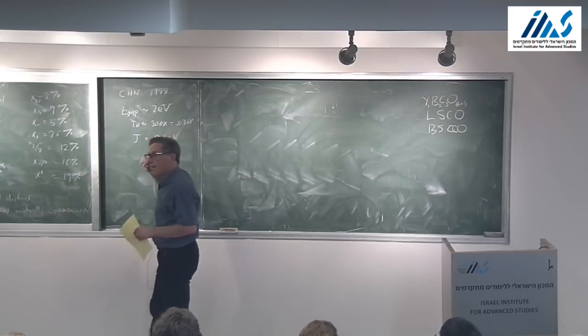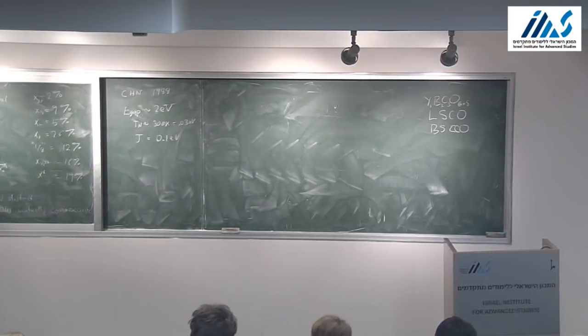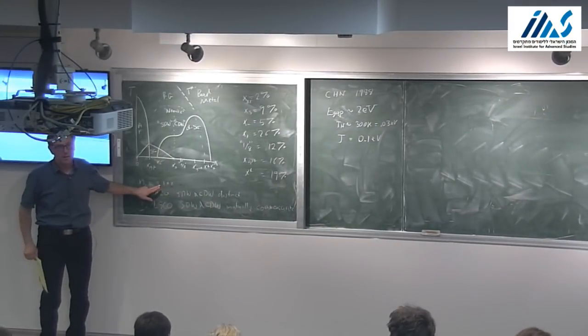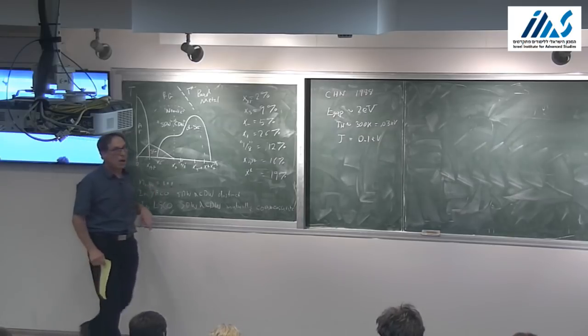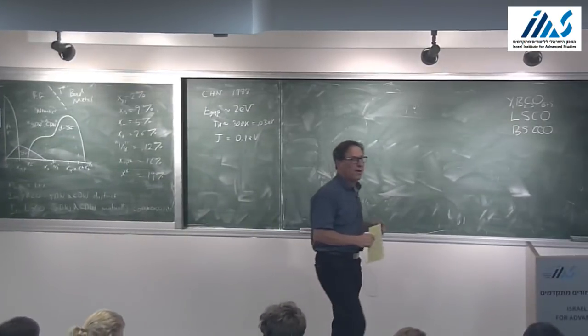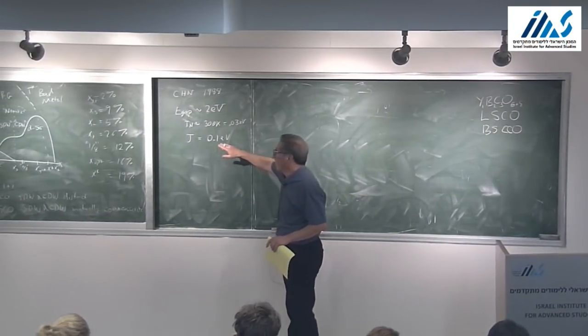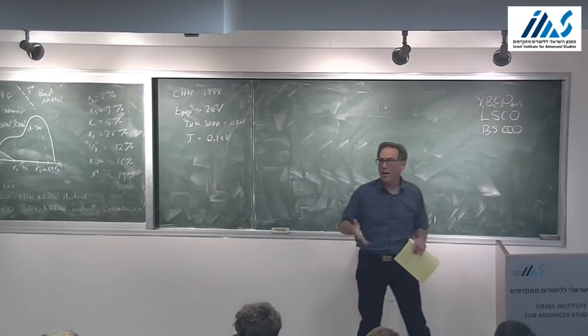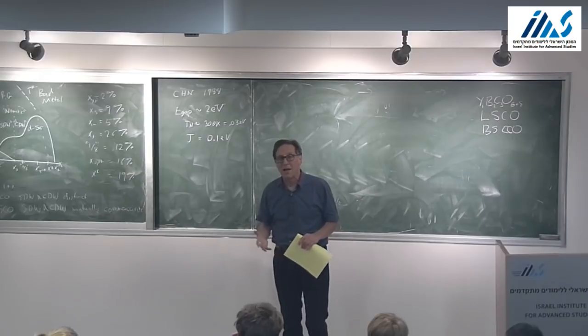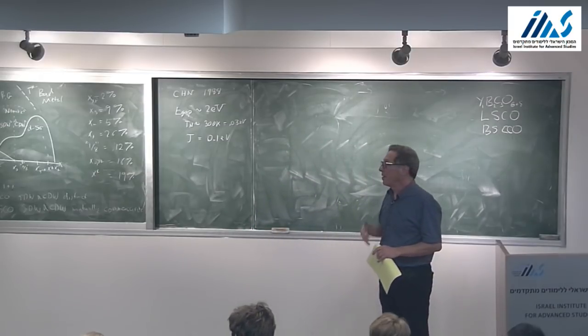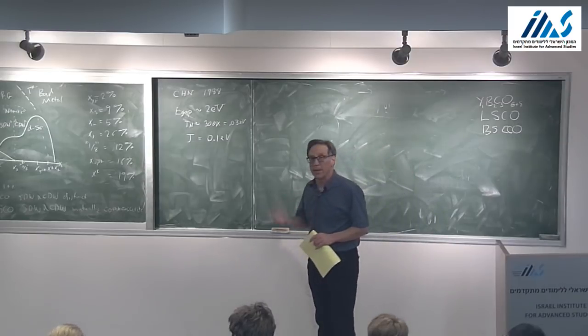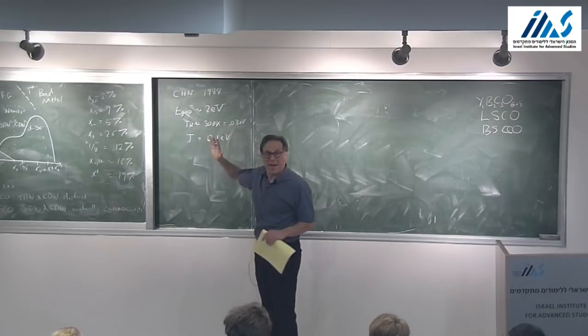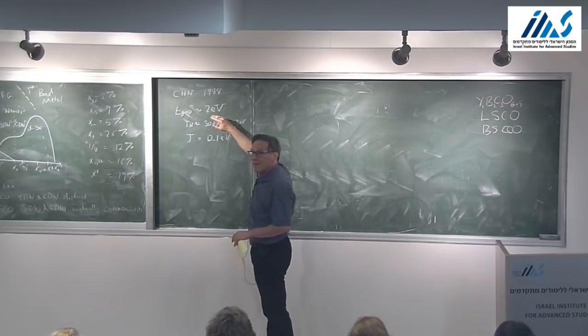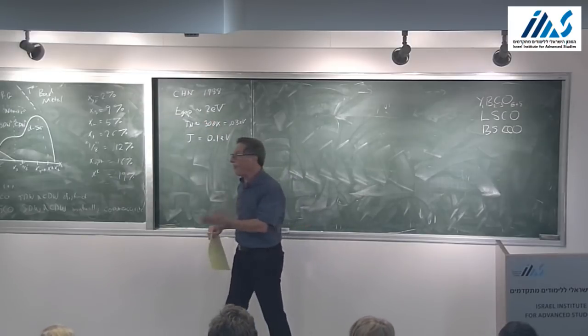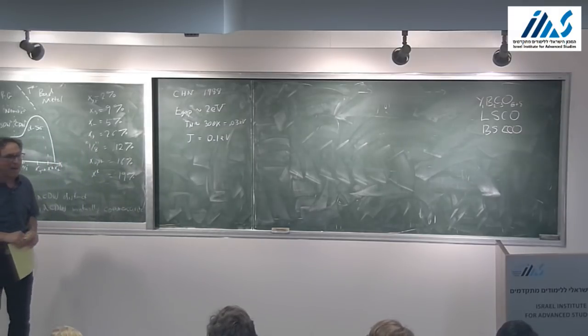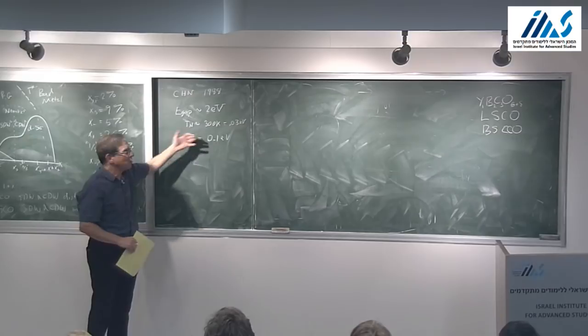Now, this gap is something you can't get out of band theory, because at x equals 0, there's 1 electron per unit cell. So the conventional solid-state physics way of understanding this would be, I'd look at 0 temperature, where this system forms a Néel ground state. The Néel ground state doubles the unit cell, so now there are 2 electrons per unit cell, and therefore the system can be an insulator and have a gap. This description of the physics is clearly completely wrong. The gap has nothing to do with magnetic order. If you want a pseudogap, it's a gap that you might have wanted to explain by antiferromagnetic order, but then it exists without that antiferromagnetic order, although at low temperature it turns out that you do antiferromagnetically order.